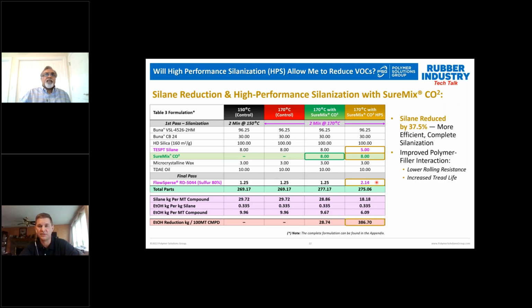Now, important thing to realize is that as we reduce the silane, by being enabled to reduce the silane with SureMix, we have a reduction in the ethanol liberated during mixing. So you may say that ethanol is just burned in our oxidizer if you have one equipped on your Banbury, but every time you burn the ethanol that's liberated, you're generating more CO2 in the environment. And there is also some left in tires liberated during use as well. So you see the reduction of almost 400 kilograms per 100 metric tons of compound with the reduction in silane that we're talking about for this formula.